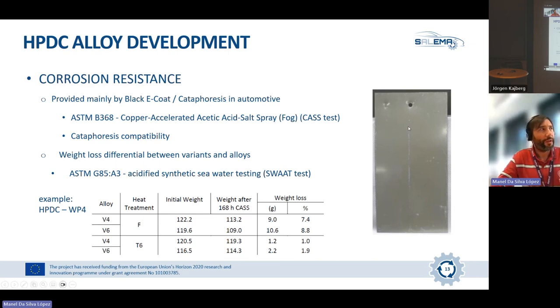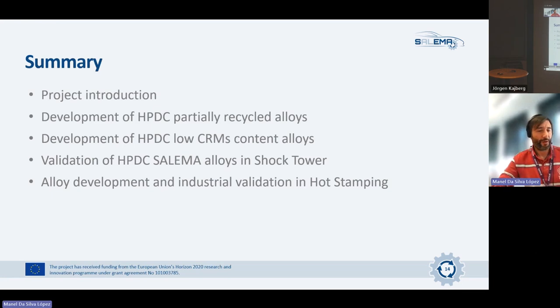We also measured the corrosion resistance, because it's another important aspect: impurities, especially copper, reduce the corrosion resistance of aluminum alloys. Here we observed that the amount of copper, or the increment of impurities, didn't affect corrosion resistance that much, and the weight loss was more or less the same. And unexpectedly, we observed that the heat treatment highly improved corrosion resistance. So a T6 heat treatment will lead to better corrosion resistance compared to as-cast properties. And this heat treatment was much more important than the impurities we will have in the alloy.